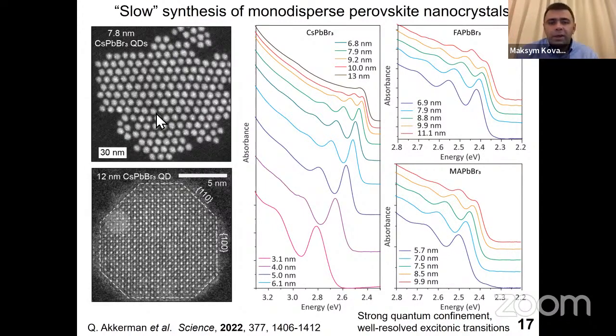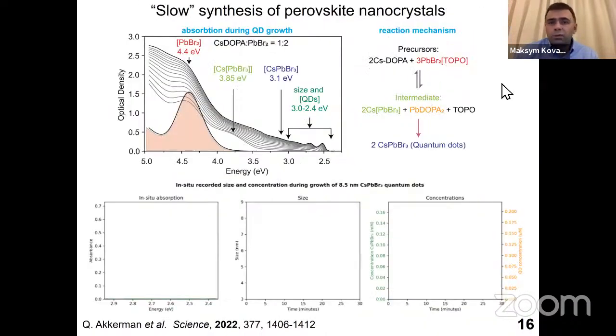But what's also very special is that your dots are no longer cubic, they can be of spherical shape. The reason is exactly what we discussed before: you no longer use amines in the synthesis. So this mechanism of 100 lattice plane stabilization doesn't hold anymore. You don't have any ligand which binds very strongly in this system, which is a blessing and a curse. It's a blessing because you can use such a synthesis as a first step to functionalize your nanocrystals with any ligand that we want. You can put any molecule that has high affinity to the surface, because in the synthesis you don't have any such molecule. So you can decouple the formation of nanocrystals from their subsequent surface functionalization.